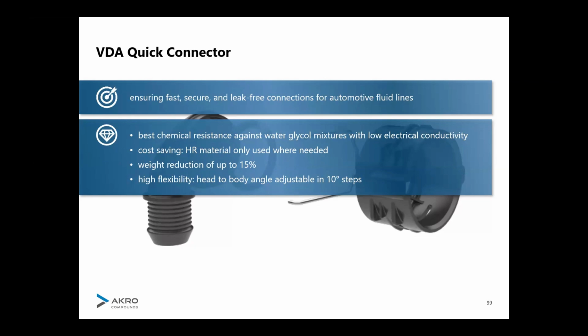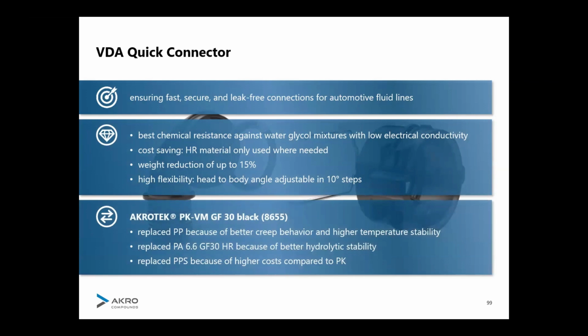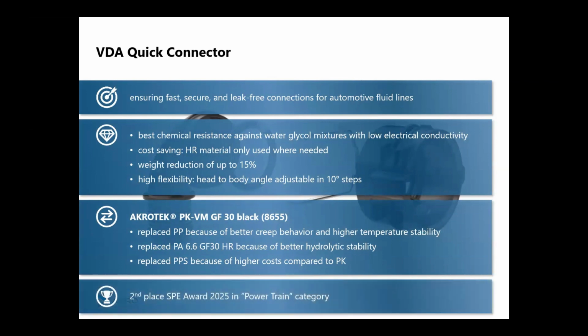And luckily, the polyketone is resistant. But the second thing is, we also need to be careful as a compounder to create materials that do not release any ions into the cooling circuit. Because if we put the wrong stuff in our formulation, then over the long lifetime, this non-conductive cooling agent can suddenly become conductive. With our PK VM GF30 black, we fulfill these requirements. Therefore, that was the decision why this material is used for these quick connector applications. These connectors also won an SPE award a week ago, second place in the category powertrain.